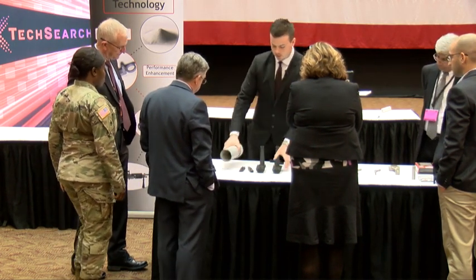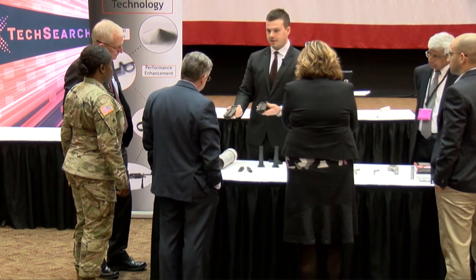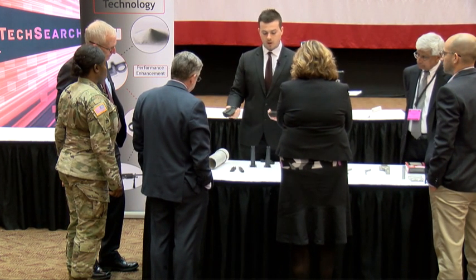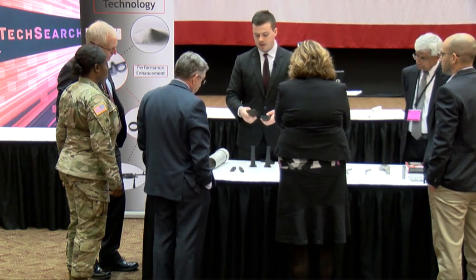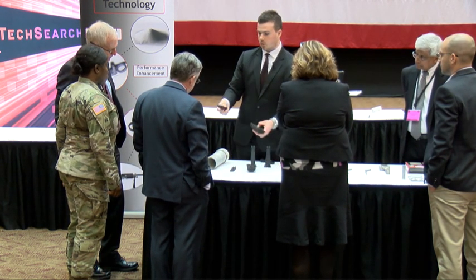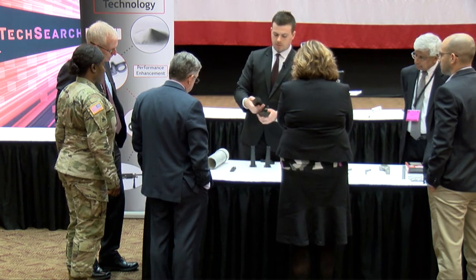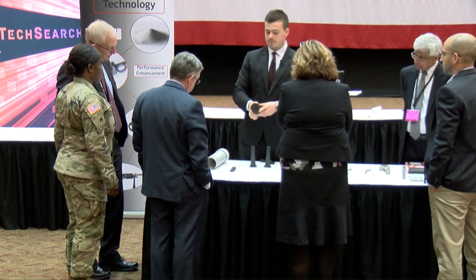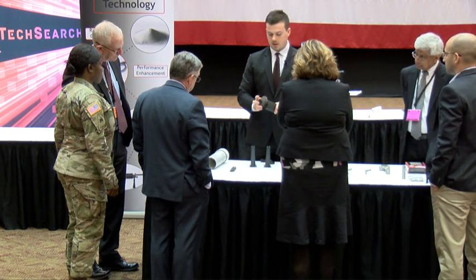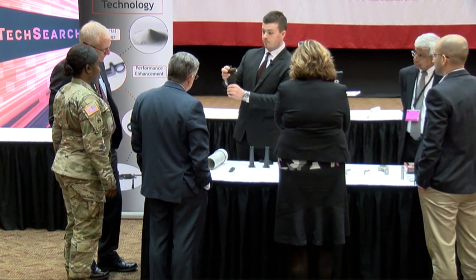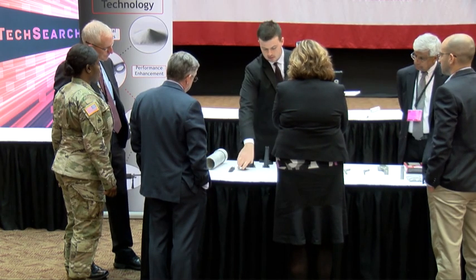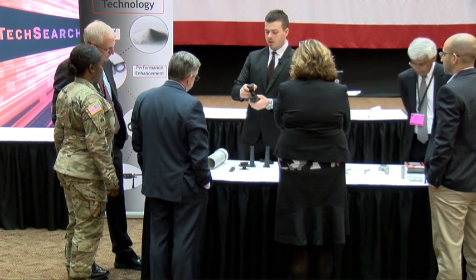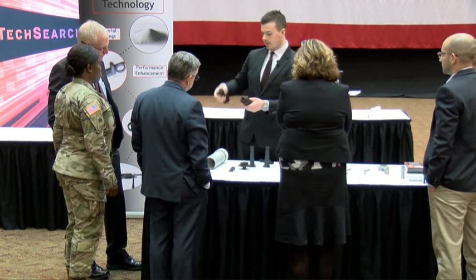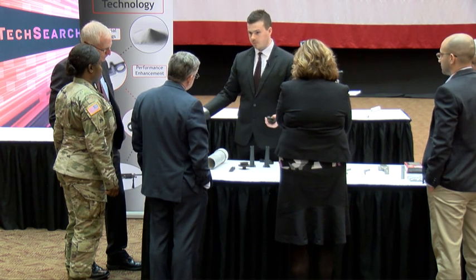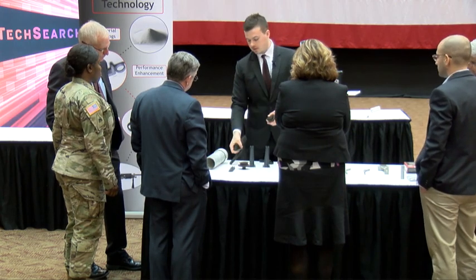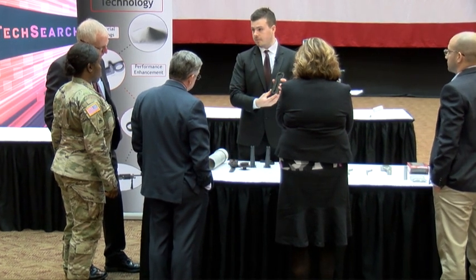So basically, picture that we could 3D print a part shaped like this. Just use your imagination for whatever part you would want. This is a connecting rod, for example. What we would do is put a bag of some sort inside this and close the part, just like so. Then you attach this onto here and fill this part full of powder. So now the inside is full of powder. You expand it with vacuum so it fills the inside of this chamber, or whatever chamber you'd want to use. And now you have a part that is full of powder in this shape.